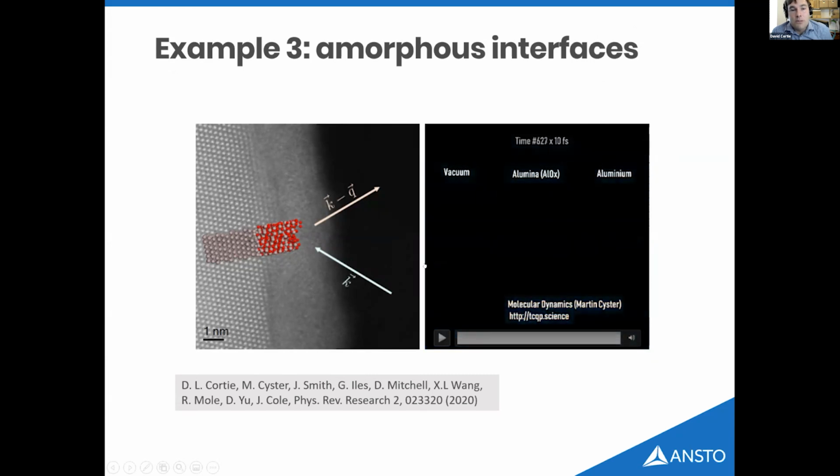So what most people do is they combine DFT with Monte Carlo or micromagnetics, and we do this as well. We extract from the DFT 0 Kelvin state the exchange interactions, for example, and the anisotropy if we're able to, and we feed these parameters into the next level of our model, which will generally be micromagnetics or Monte Carlo, where we have temperature built in more rigorously. So we have done some of that work. The reason I didn't talk about it so much is that we haven't got a perfect pathway for doing that. We haven't got a standard way of doing that yet, whereas at least with the DFT, it is kind of standard now. Okay, thanks.